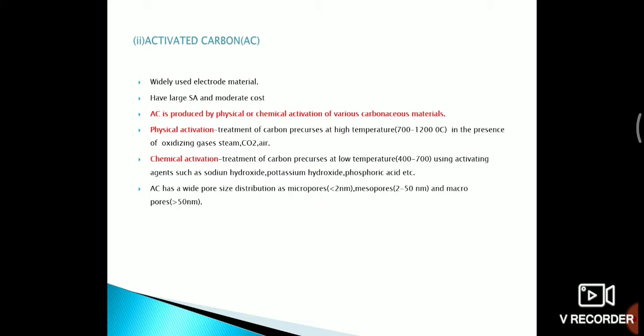Activated carbon is produced by physical or chemical activation of various carbonaceous materials, like wood, coal, nutshells, etc. Here, physical activation includes the treatment of carbon precursors at a high temperature of 700 to 1200 degrees Celsius in the presence of oxidizing gases like steam, CO2, air. And chemical activation includes the treatment of carbon precursors at a low temperature of 400 to 700 degrees Celsius using activating agents such as sodium hydroxide, potassium hydroxide, phosphoric acid, etc. This activated carbon has a wide pore size distribution of micropores, mesopores, and macropores.